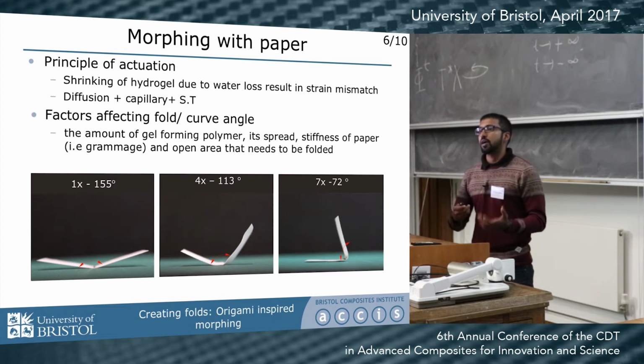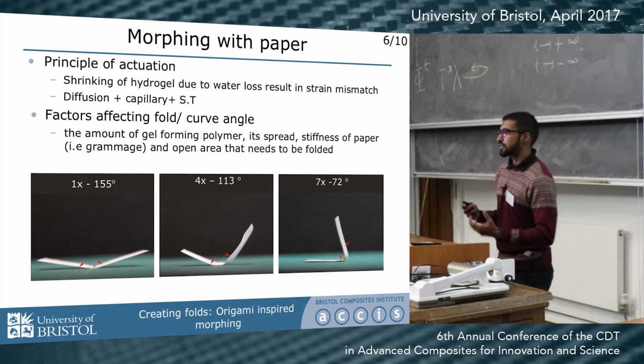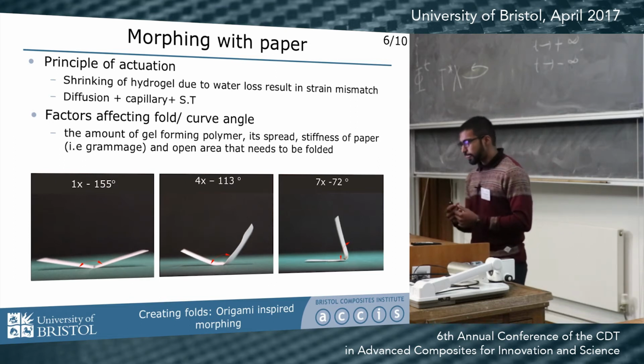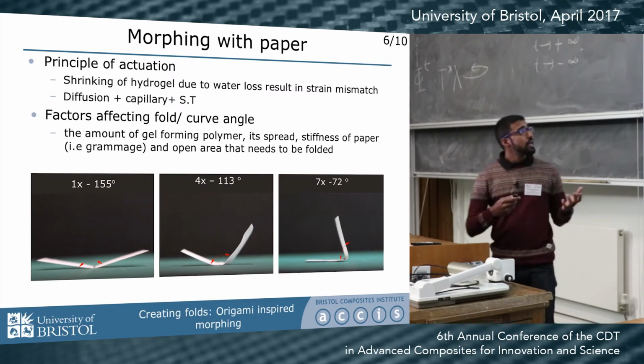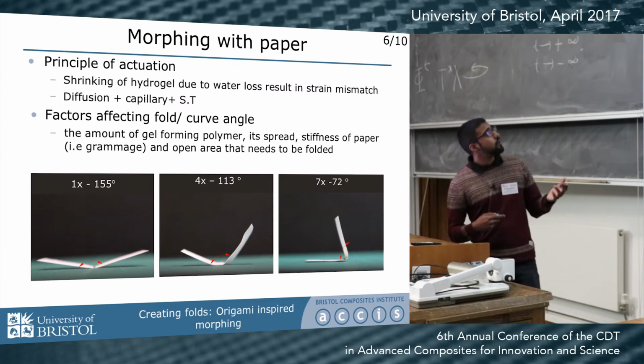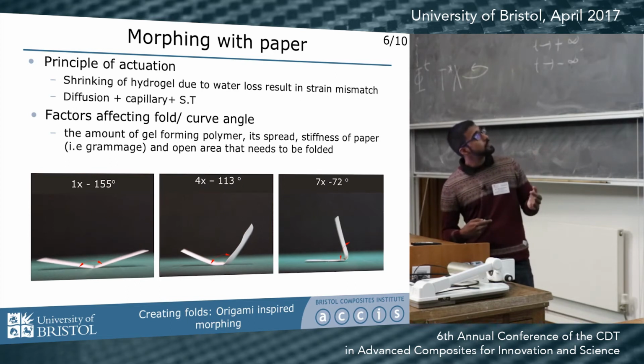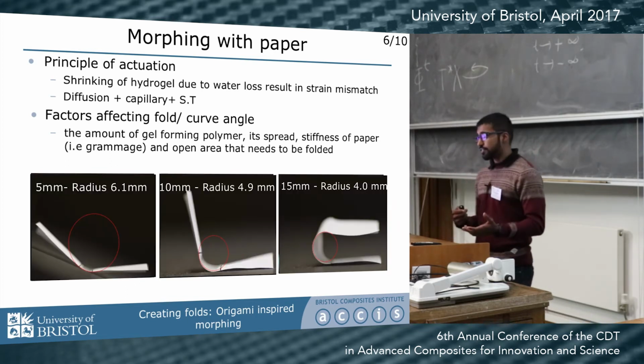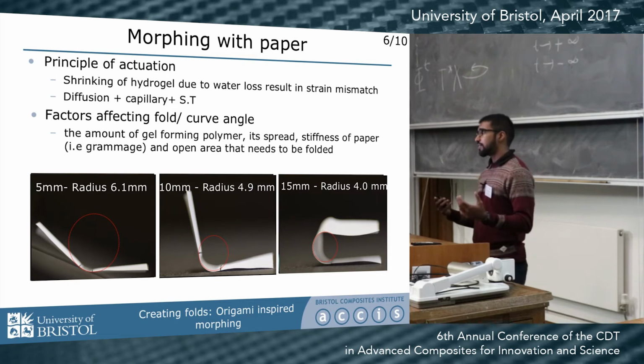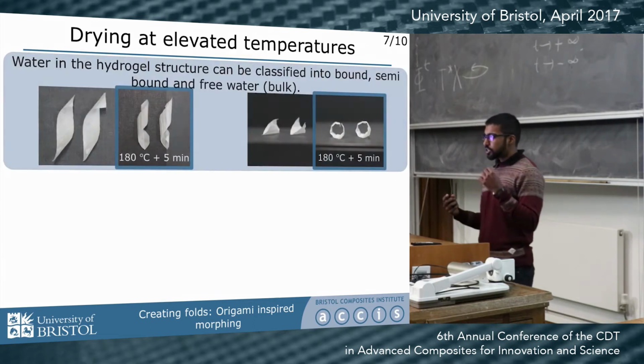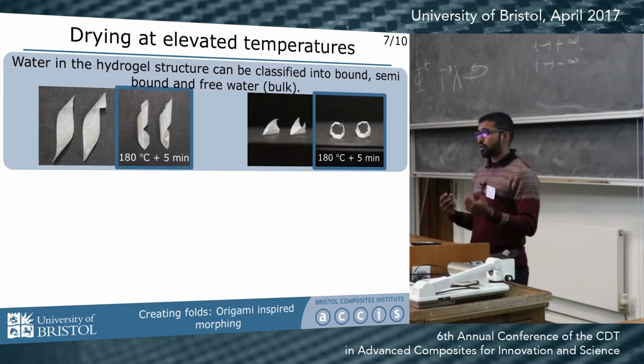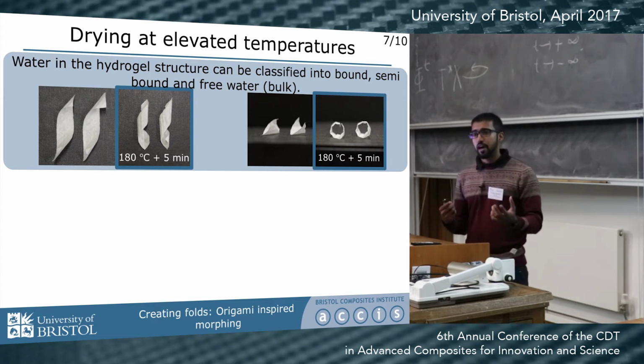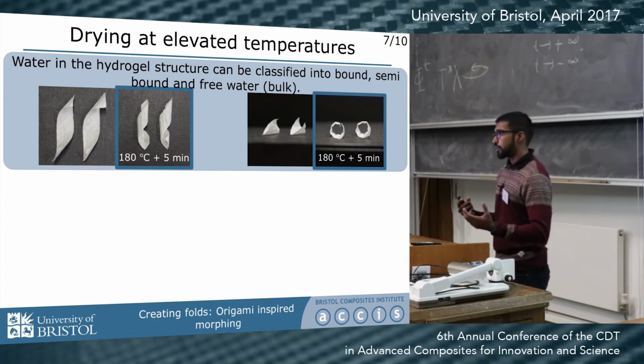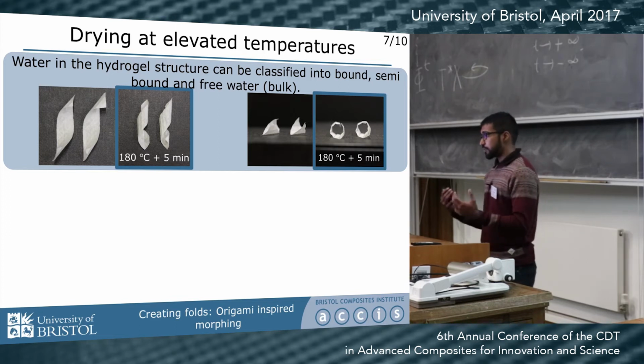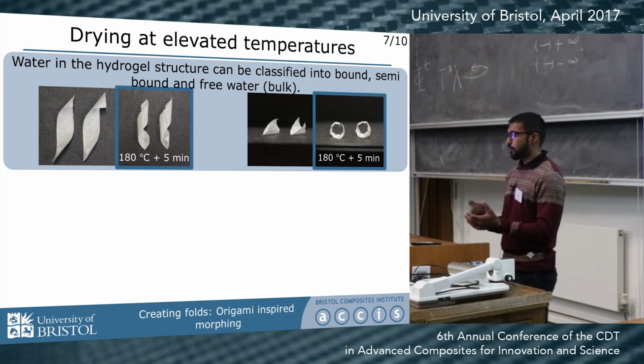It's a diffusion-dominant drying mechanism assisted by capillary forces and surface tension of the gel. The fold angle is shown to be dependent on the amount of gel-forming polymer, its spread, and obviously the stiffness of the paper and the area that needs to be folded. Drying at room temperature only removes the free water within the hydrogel. However, drying at elevated temperature removes the bound water from the gel, resulting in greater shrinkage, maximizing the morphing behavior.